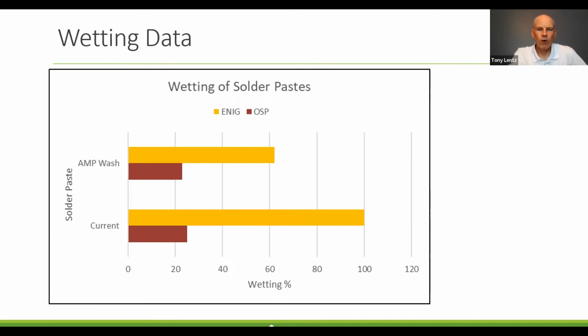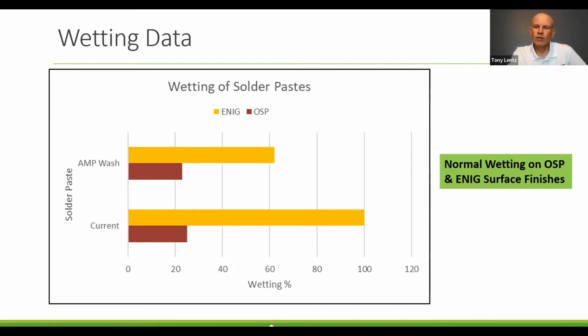On ENIG, amp wash and the current solder paste are definitely a little bit different. The current solder paste actually wets and spreads very far on ENIG, whereas amp wash spreads a little over 60%, which is pretty typical of a lot of different solder pastes. Both are more than adequate for wetting both OSP and ENIG surface finishes.